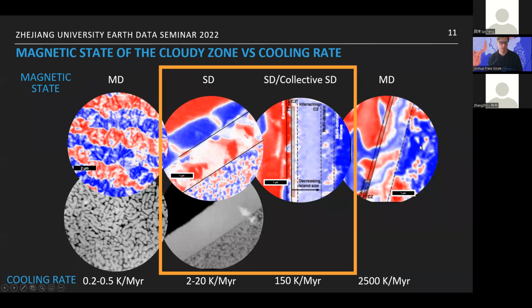And the thing that's really important is that we could find that if we cooled between about 2 degrees Kelvin per million years up to about maybe 150 degrees Kelvin every million years, we actually get really good magnetic records in the cloudy zone. If it goes much slower than the 2 degrees, the cloudy zone just gets so big it becomes interacting and the magnetic information is not reliable. Likewise, if it cools too quickly, the magnetic information is not written correctly.